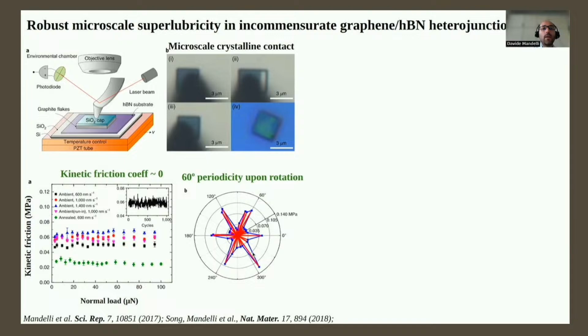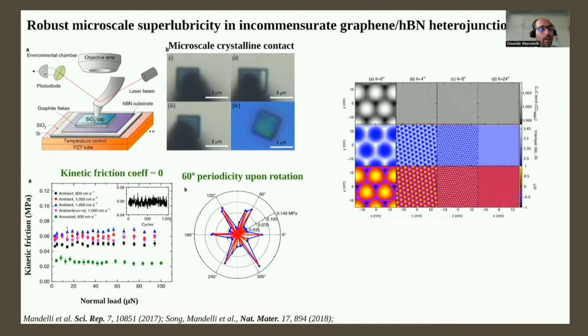They also performed simulations as a function of the orientational angle. They measured friction as a function of the orientational angle, and they found this 60-degree periodicity, which is actually connected again to the dependence of the mass density waves on the angle. Again, I am almost out of time, so I will just point out the main feature.